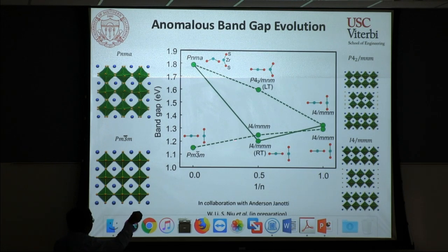In that case, if we compare the trend with only quantum confinement, we do see an increase in the band gap. But in reality, the system actually likes to distort a lot in the perovskite form, and as you make it lower dimensional, the distortions go away, and hence your band gap drops. That is very clearly shown with the theoretical calculations also. So this tells you that in these materials, not only does the connectivity of these octahedra matter, even subtle distortion and rotation can affect your optical properties significantly.